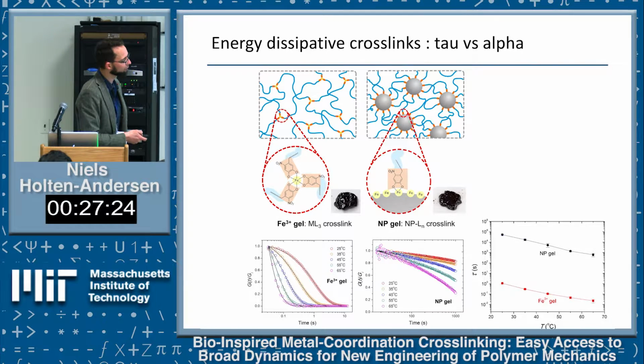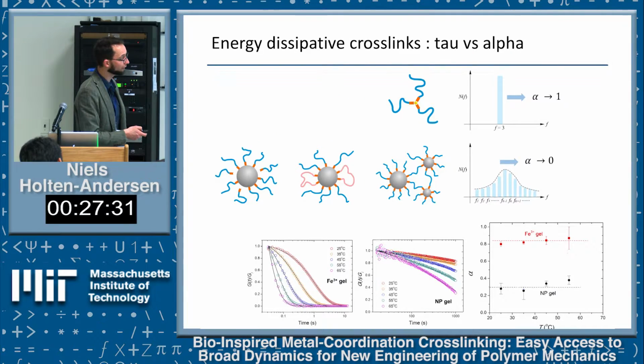If we heat these networks, it's still much more solid-like for the nanoparticle gel than the metal ion gel. If we look at this alpha value, as expected, the metal ion gel has a high alpha value, meaning a narrow distribution, meaning not a very tough material. The nanoparticle gel, on the other hand, is a much tougher material with a broader distribution, and again this comes from using these nanoparticle crosslink structures.